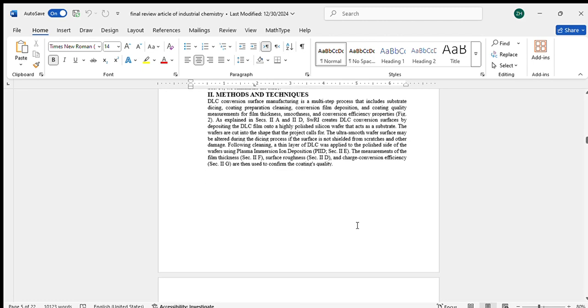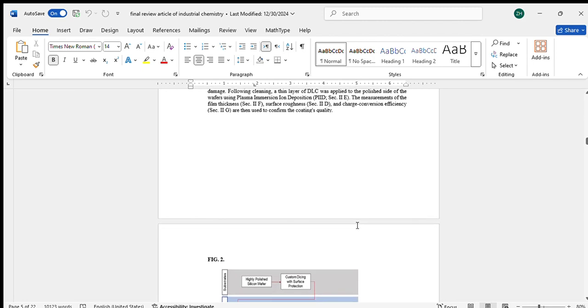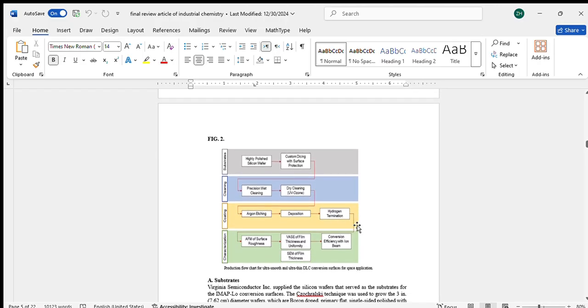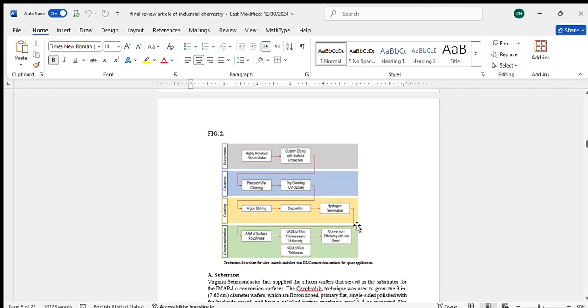where the roughness increased from 0.47 nanometers to 2.68 nanometers due to the contamination. After cleaning, the roughness returns to 0.35 nanometers, demonstrating the effectiveness of the cleaning process.